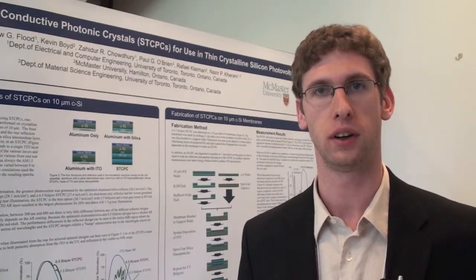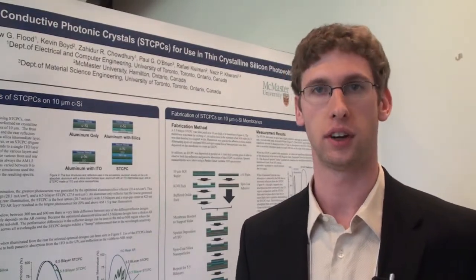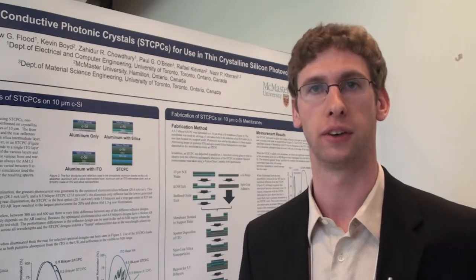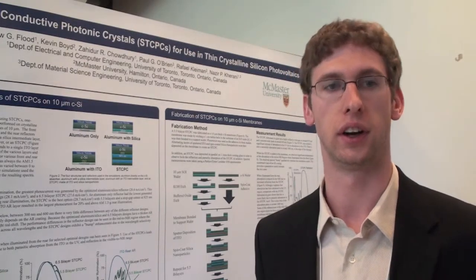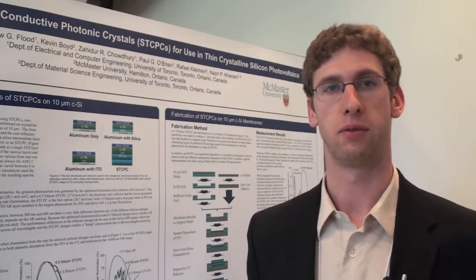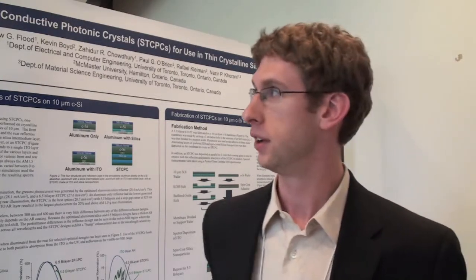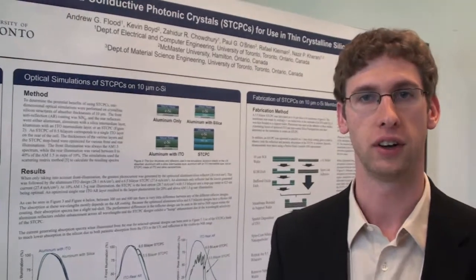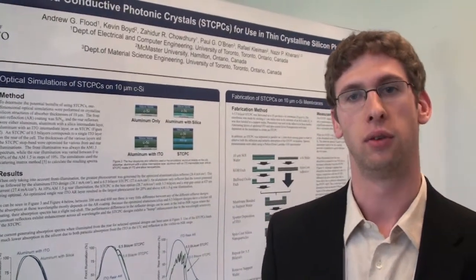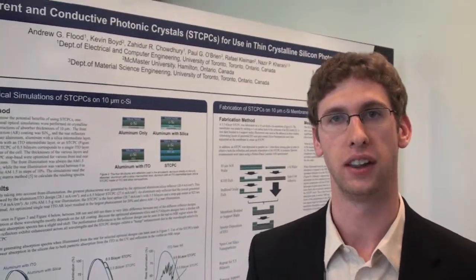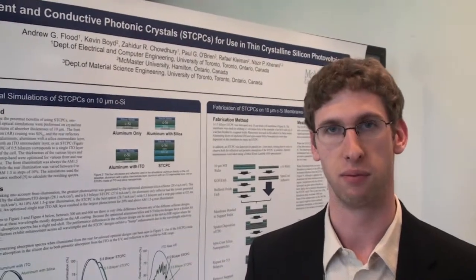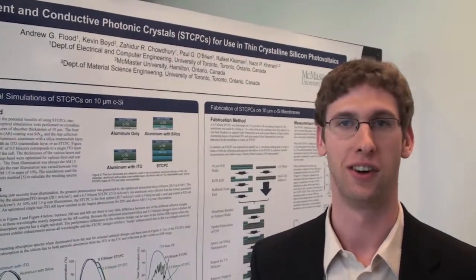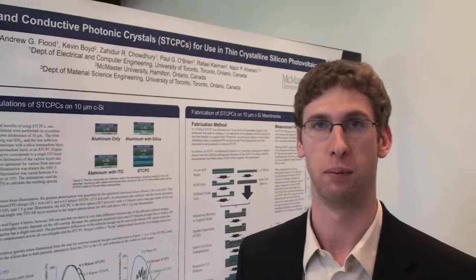The research we're doing is on bifacial silicon cells and novel reflectors that are both conductive and transparent in certain wavelengths. One of the problems with current reflectors, say an aluminum reflector, is that in bifacial cells, when you have illumination from both the front and the rear, you get no improvement from the rear illumination, obviously with aluminum or metals being opaque.